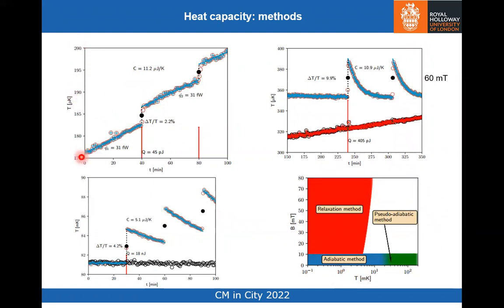So this is temperature as a function of time, starting off at 175 microkelvin. There's the warm up of the sample in a heat leak of 31 femtowatts. This tiny heat leak is achieved by extremely good shielding and screening of leads in the sample. And then we apply a small heat pulse. So that's effectively the adiabatic technique. And then there are other techniques that are used in different parts of the phase diagram.